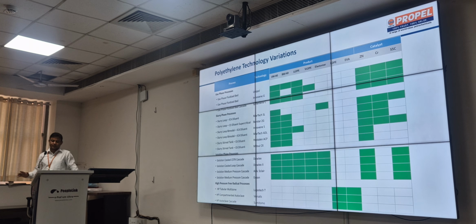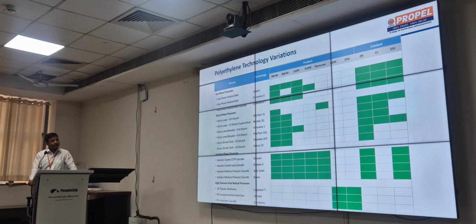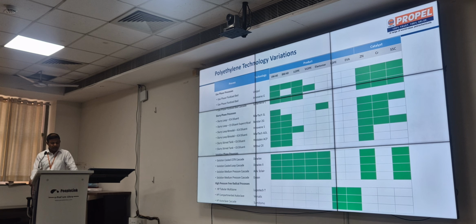Some of the technology variations in polyethylene technologies: in the gas phase process, there are Unipol, Innovene and Spherilene. You can get unimodal HDPE, bimodal also, and LLDPE, with catalysts like Ziegler-Natta, chromium and single site catalyst. In Innovene's case you cannot get bimodal products, but in Unipol you can get both unimodal and bimodal. With the gas phase process by Spherilene, you can get the whole range of density. You can produce LLDPE, and you can produce medium density polyethylene, which is very important in gas pipe applications, like city gas distribution. Medium density polyethylene pipe grades are used for such applications.